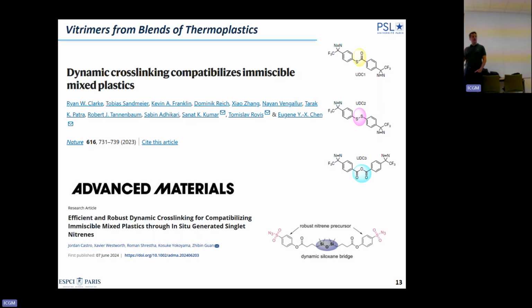And here's the trick, which is not a simple trick, is to introduce this group, which under the action of heat or light will decompose, it will release nitrogen, and you create a carbene. And carbenes are pretty reactive, as we know, and they can insert into CH bonds, and then you can more or less modify almost everything. So this is really the trick. Very nice work. Very nice work. I wish it would have been us.